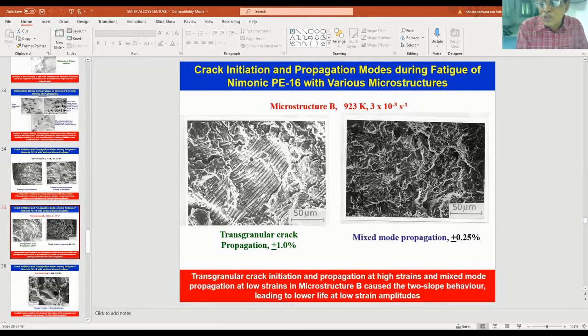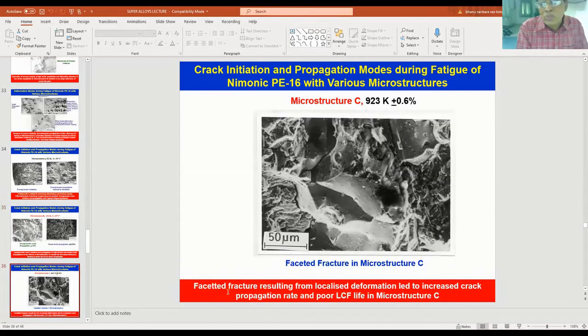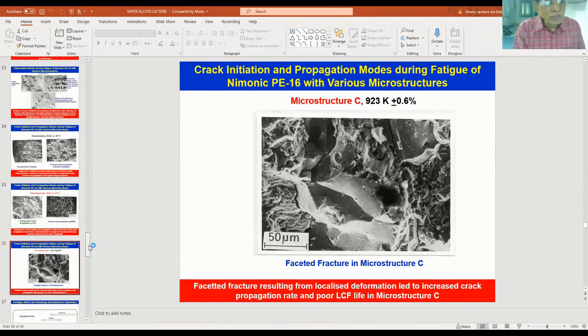So that is in the double-aged condition, microstructure B. In microstructure C, where the precipitation of fine gamma prime is coming during testing, you see the faceted, cleavage-type fracture occurring like this. So the composition of the material is the same, but you have given different heat treatments. If the material is going into service in different heat treatments, it will have its effect on the fatigue resistance of the material. That is through the deformation and fracture that is occurring.